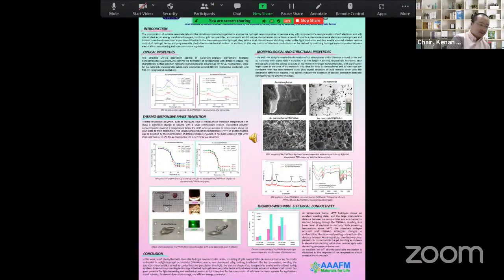Two different shapes of gold nanoparticles were incorporated into a cross-linked polymer matrix, and the obtained hydrogel nanocomposites show typical absorption spectra with the two characteristic absorption bands for gold nanospheres and nanorods. SEM and TEM analysis confirmed the formation of gold nanospheres with a diameter around 20 nanometers and gold nanorods with aspect ratio about 5. Thermoresponsive polymers have a critical phase transition temperature and show a significant change in volume with a small temperature change. Below this temperature they swell, but above this temperature they shrink.